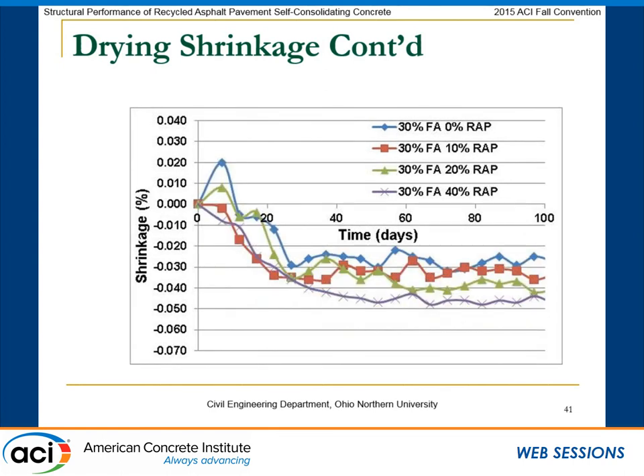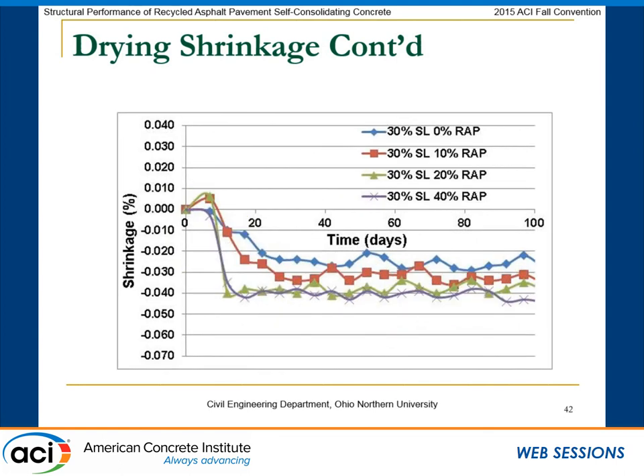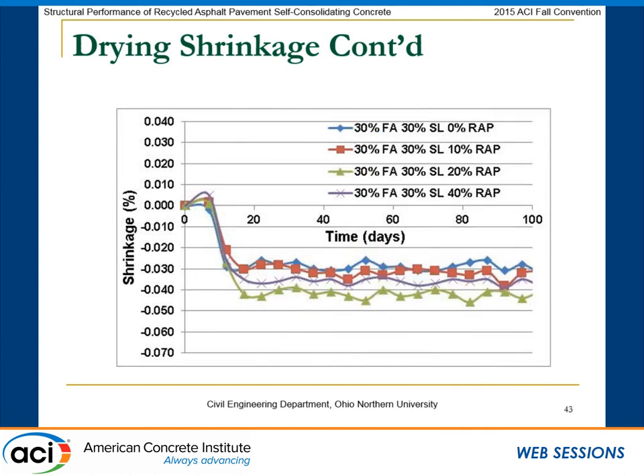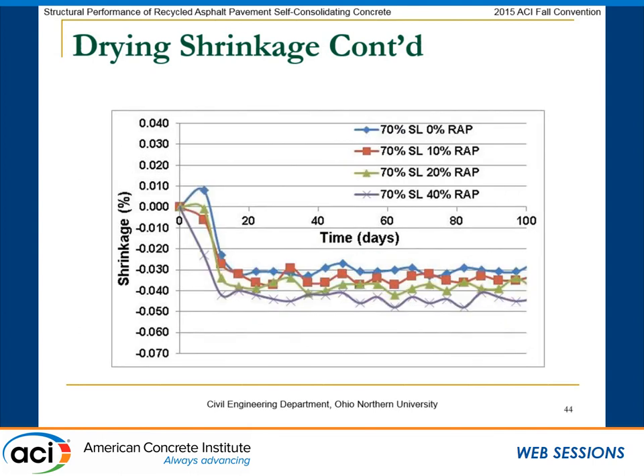30% fly ash, you had a smaller strain than 20% fly ash, but the same trend. 30% slag, you have a smaller strain than the fly ash, okay, but the same trend as you increase the RAP, your strain increases. And then 30% fly ash, 30% slag, you had a smaller strain than the 20% fly ash by itself. 70% slag, still smaller than the fly ash, and the same trend can be observed for the strain.